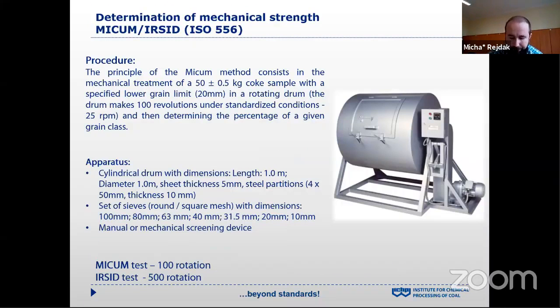The principle of determination of Micum or IRSID parameters is based on mechanical treatment of a coke sample in a rotating drum, and then assessing the mechanical strength. When we talk about Micum, the test equals 100 rotations. In case of the IRSID test, there are 500 rotations of the drum.